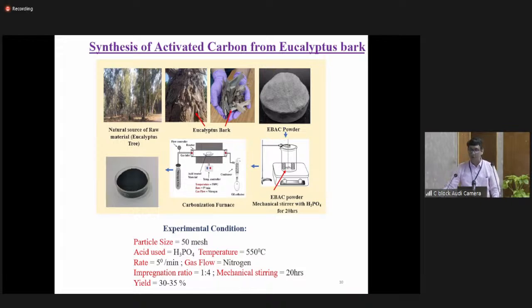Eucalyptus bark powder, and then you make a powder of that. The powder size is around 50 mesh. This is passed through the 50 mesh screen, and then we need some kind of activation material. The activation agent we are taking is orthophosphoric acid, and the temperature was kept at 550 degrees centigrade, but basically optimized from